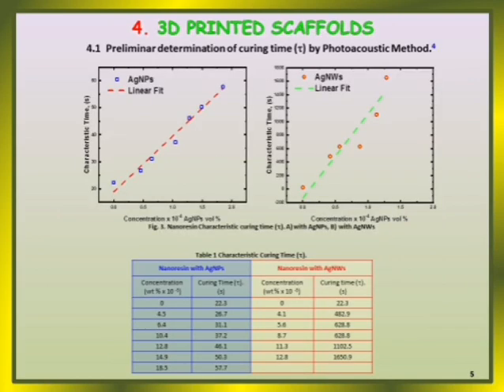We used the photoacoustic method to determine whether there was a variation on the characteristic curing time, tau, among the nanocomposites and the original acrylic resins. We can find details about the photoacoustic method in reference 4. We found that tau changes proportionally to the nanostructure's concentration in the acrylic resin. In both cases, with silver nanoparticles and with silver nanowires, a linear trend can be drawn.